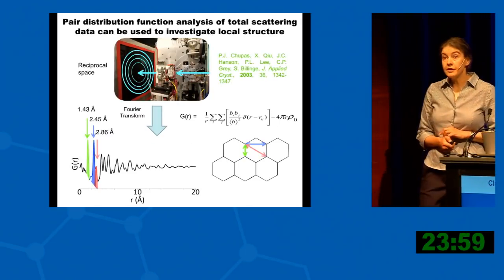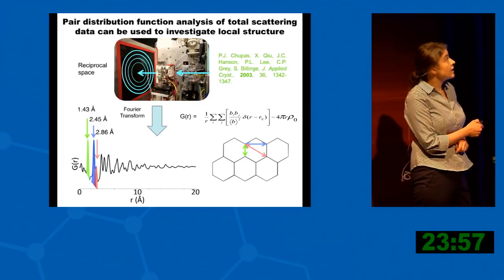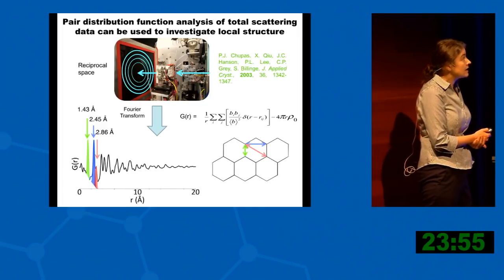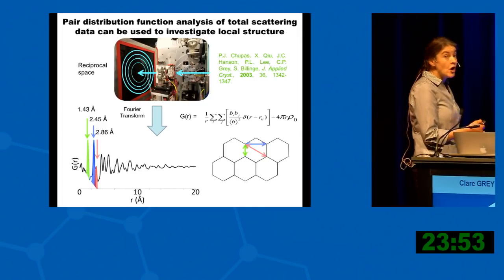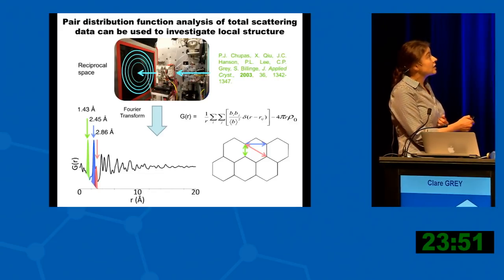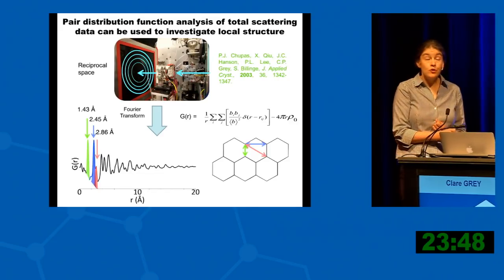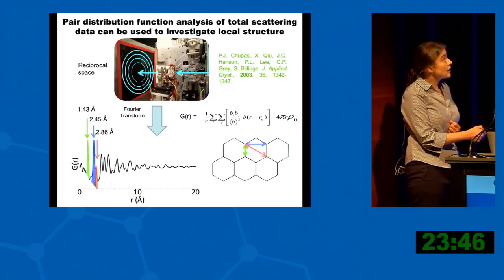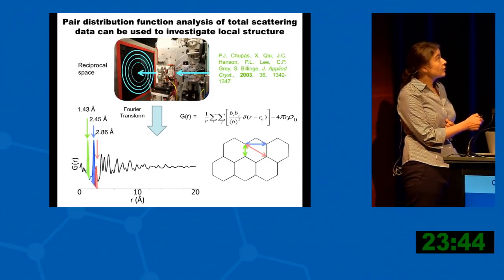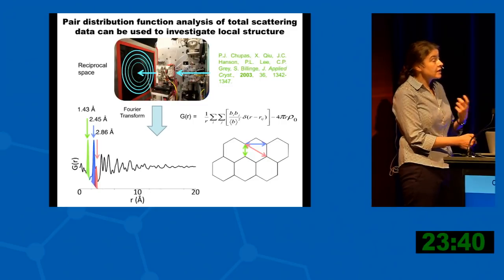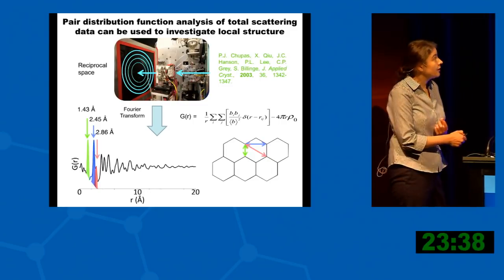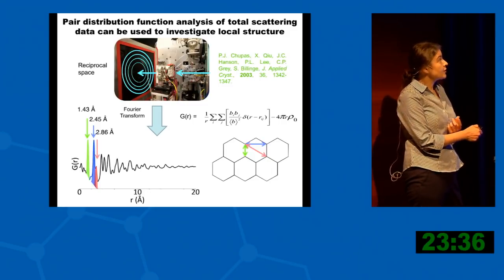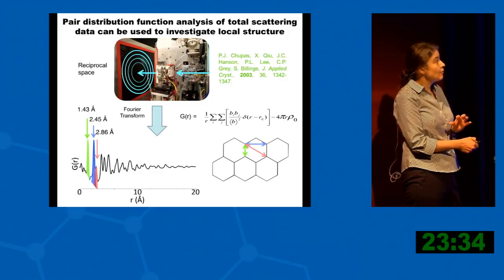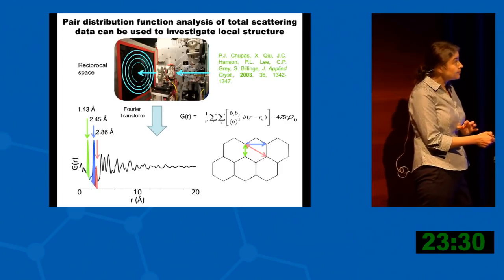And so what we've done over the last few years is to use a technique called pair distribution function analysis, where you can take the total scattering pattern collected in a synchrotron source or in a neutron source. We do a Fourier transform, and we convert reciprocal space into real space, and then you get a series of correlations that tell you something about the local structure. And so for a carbon, the first peak you get here is the carbon-carbon bond, the second one is the cross-ring, and so on.